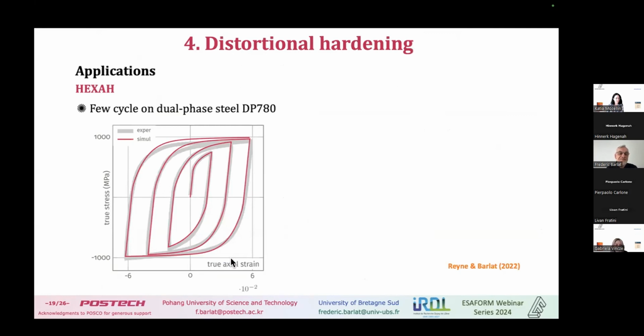And with HEXAH, we also get good simulation results. Here, this is the experiment, the gray line. So this is a few cycles, but it's only one curve here. And the simulations are in red. Now, one thing is this data was fitted manually with some trial and error. But what I want to say is we didn't need much effort to calculate the coefficients to get this red curve. If we want to be more accurate, maybe we can do better with some optimization tool, but at least this red one can be the initial estimate, the initial curve, and in this case, we probably can do a good job with an optimization tool.